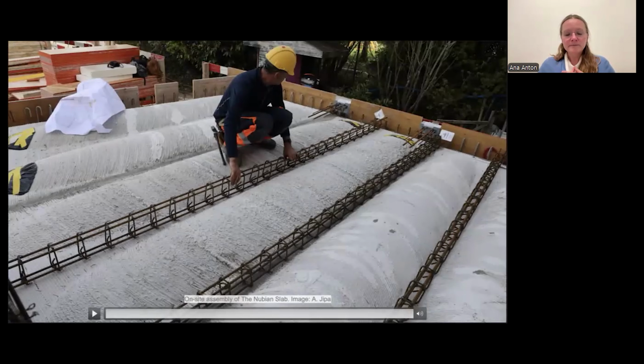With this simple project, in a way, we also proved that we can reduce the use of concrete. Having these vaults enabled us to reduce the material by 20%. And this value could even increase if we talk about larger spans and thicker slabs that have larger structural depth. This is all about the Nubian slab.